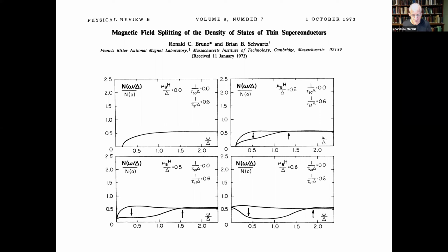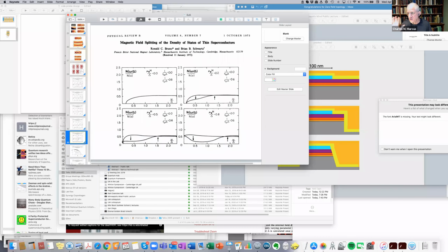So now this omega variable, the system still has an order parameter, interestingly. It still has a delta. It's not driven normal, but the omega that describes the gap in the density of states has vanished. So we have to keep all of those different quantities in mind. And I was cheap by referring to just one delta, but the delta that I was referring to earlier on is the delta of the order parameter, not the gap in the density of states. Okay, so good. Let me go back and start talking a little bit about experiment.